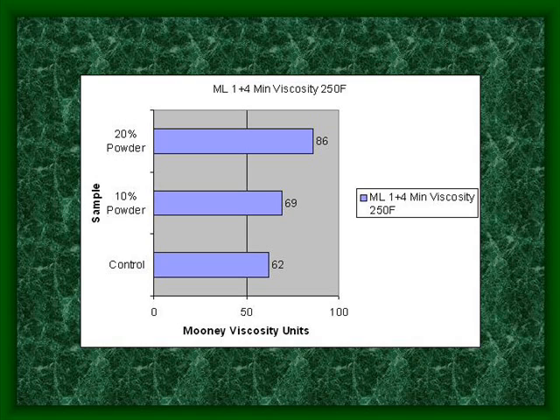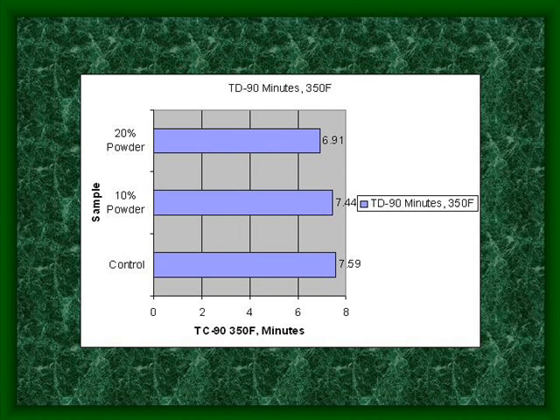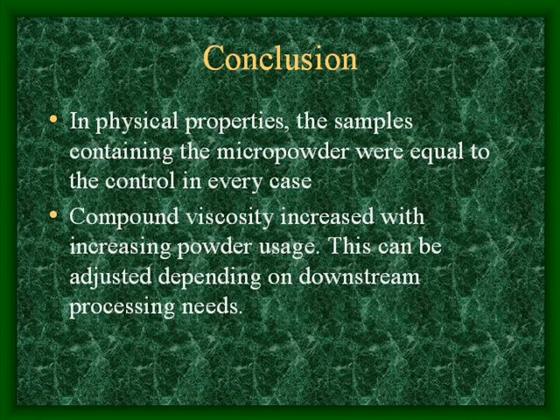The lone difference in this experiment that was powder dependent was the Mooney viscosity. Mooney viscosity increased with higher powder loadings. This is what we see all the time when we're working with micropowders. We also saw slightly faster cure rate, which corresponds with the higher viscosity and is also quite common. In physical properties, the samples containing the micropowder were equal to the control in every case.